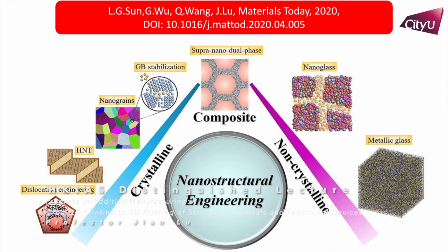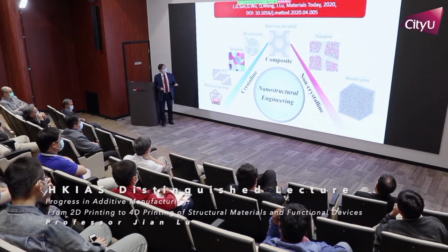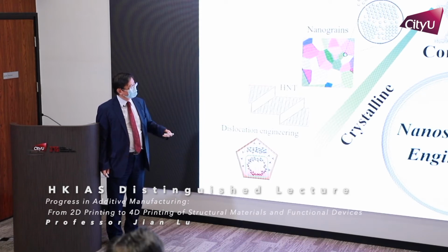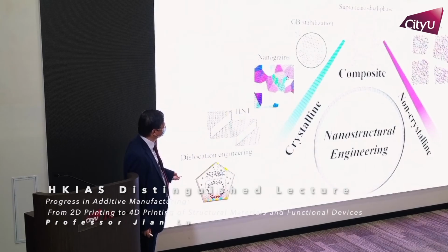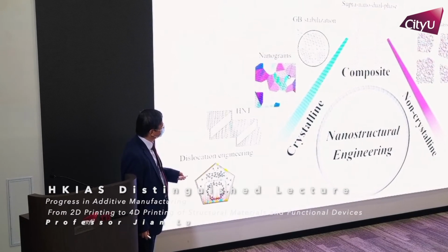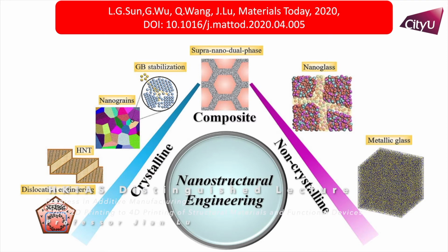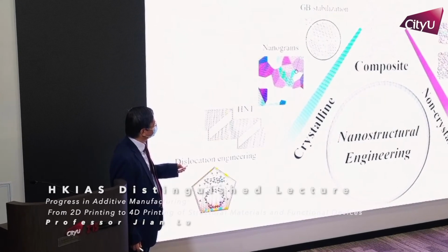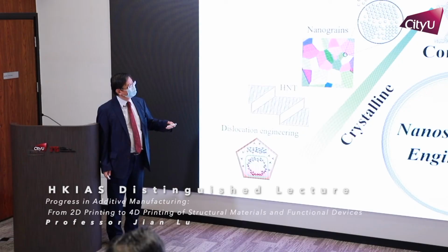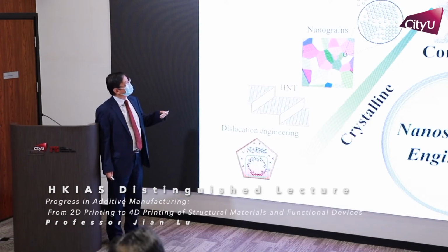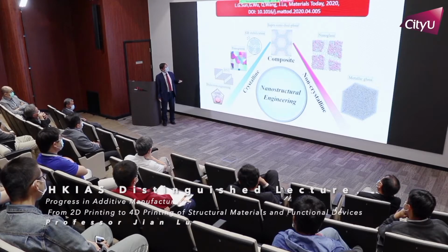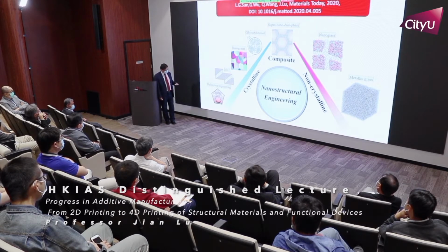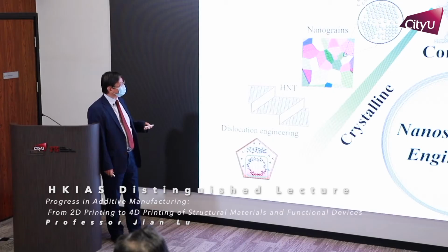So basically, for the material I will talk about today, we mainly start from different types of materials. We can call it nanostructural engineering. So we can start with a material like a metallic glass, so without any order inside of the structure. Then if you partially organize the order, you may have a nano crystal with glass. In this side, if you generate grain boundary stabilization, we can generate locally heterogeneity, and also high hierarchical nanotwin is another type of the nanostructure.